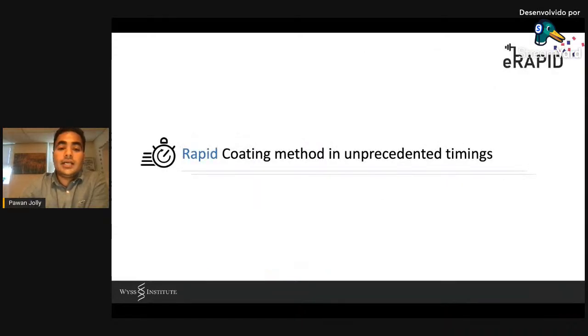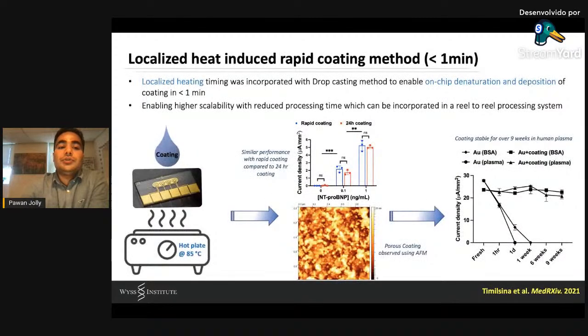Initially our coating used to take 24 hours. We used to drop cast on the sensors and leave it for 24 hours, which is not really that exciting when you have to think about commercialization. So we introduced a new method of localized heating and optimized our coating even further. By using just this localized heating, we were able to reduce the time from 24 hours to less than a minute. So we can now scale it on a very large scale, and this can also be incorporated into a reel-to-reel process system.